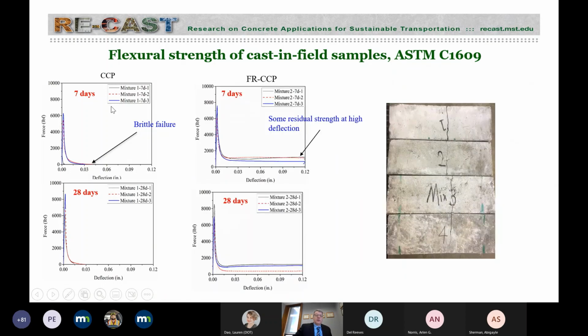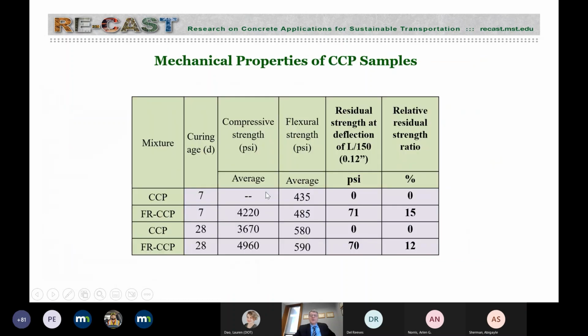This is without any fibers, and with the fibers, you get a small residual strength, less than 20% at a very high deflection. So again, at 7 and 28 days. So if we compare the flexural strengths, we have the CCP 435 flexural strengths, residual strengths, of course, 0%.